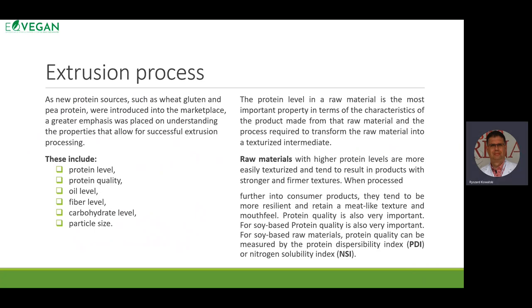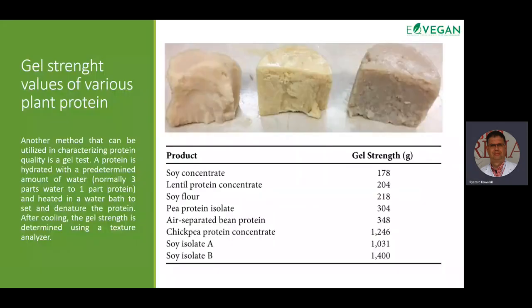If the raw materials have a lower PDI, more mechanical energy often is required to effectively texturize the material. Also, the PDI test can be utilized for other raw material sources, such as pea and chickpea. It does not fully capture the ability of a protein to gel and be texturized. After cooling, the gel strength is determined using a texture analyzer.